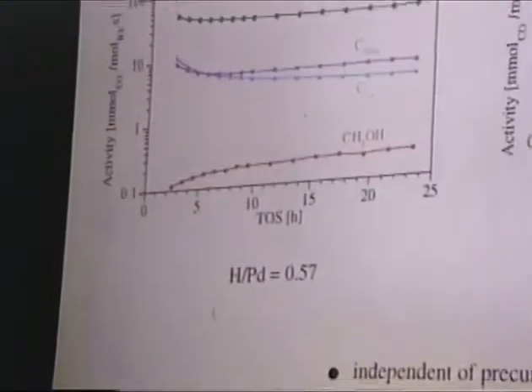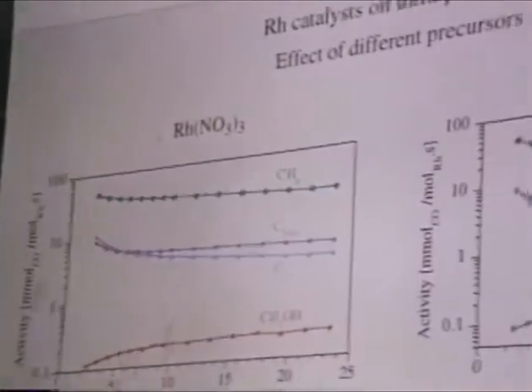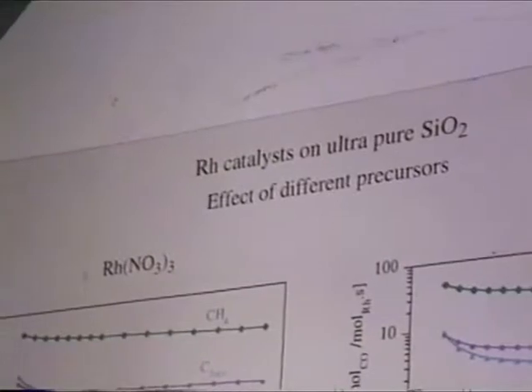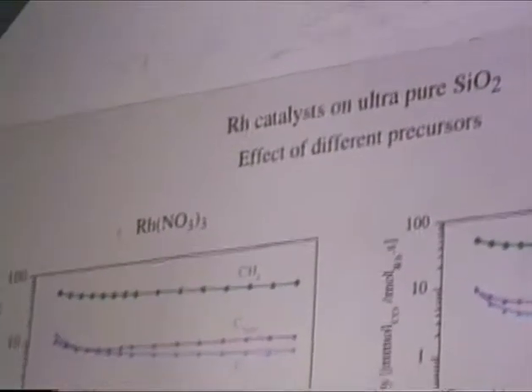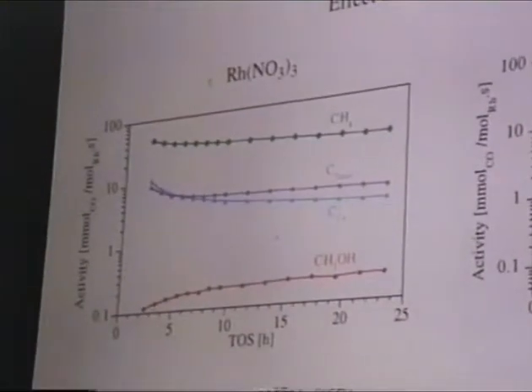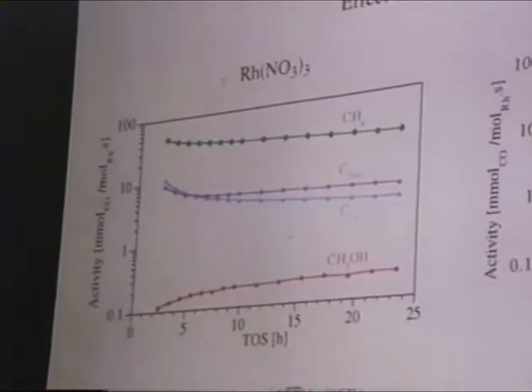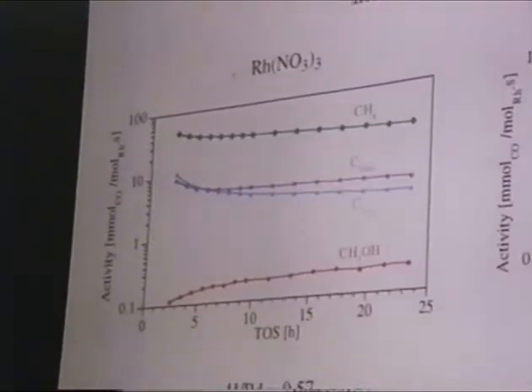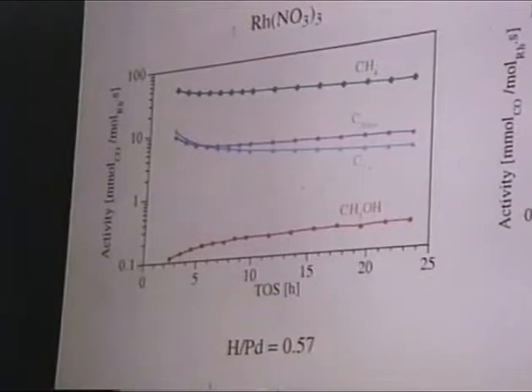Because of many articles suggesting that it's important to look at the precursor, we had a very close look at the precursor, and in our hands there is no difference between a rhodium nitrate and a rhodium chloride if you really do the work carefully and if you really take a pure silica. So part of the answer why some authors come to different results may be in the impurity on the silica.